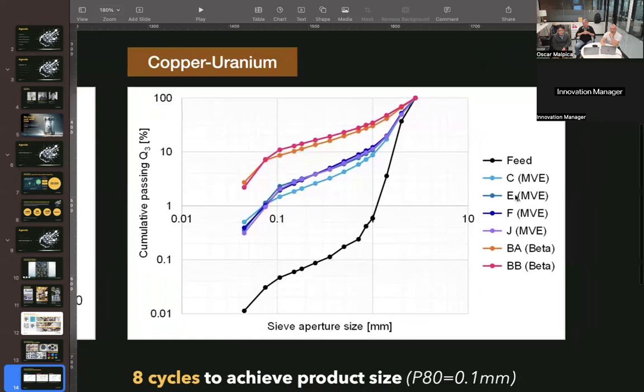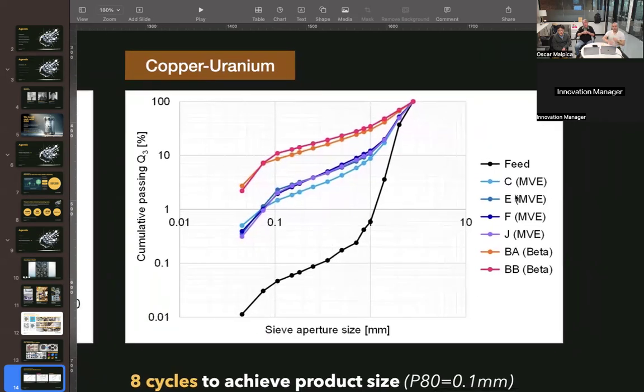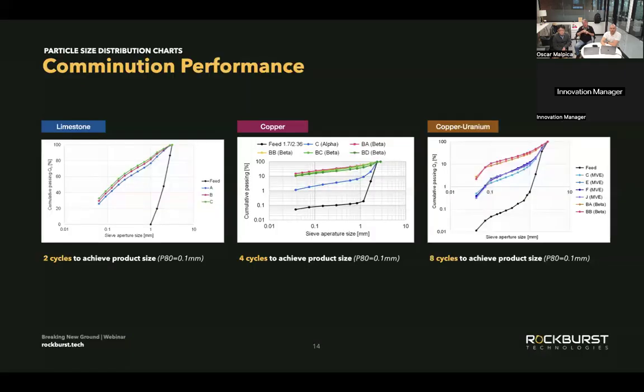So the last one here is copper uranium ore, very hard ore, quite challenging to break. The feed looks like it was essentially 1 millimeter to 3 millimeter roughly. Again, we've got an old test apparatus with that bundle in the middle of colored lines showing about 2% breakage at the 100 micron size. But then we're showing also the beta results at around the 10% mark. So in other words, with this one, to reach a P80 of 0.1 millimeter, you would need to run, say, 8 cycles, and that would push that up to the P80 mark. And when we run these number of cycles and the pressure and temperature and so on through our thermodynamic calculator, we can see what looks like very promising energy results.